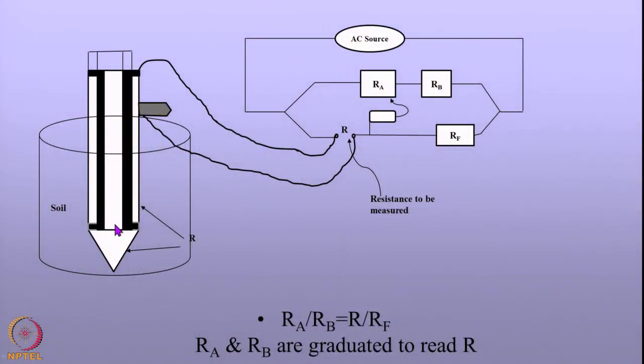You can use a two electrode system, in which case instead of using a DC, we use an AC current. And AC current does not polarize the electrodes. They are pierced in the soil or immersed in the electrolyte. So, this is a rod that is inserted into the soil actually, and the resistance between these two points is measured using a Wheatstone bridge kind of circuit.